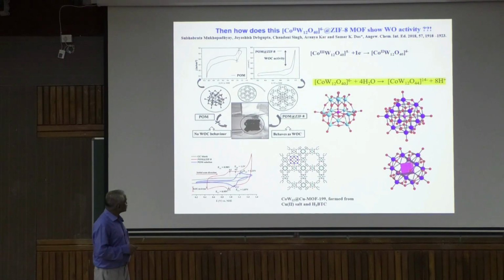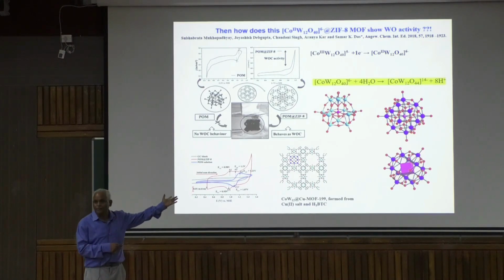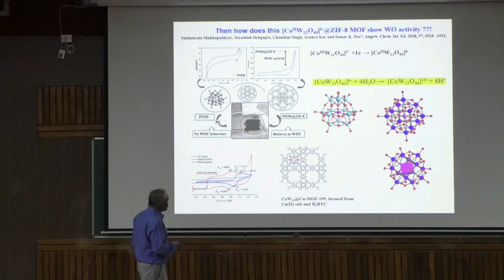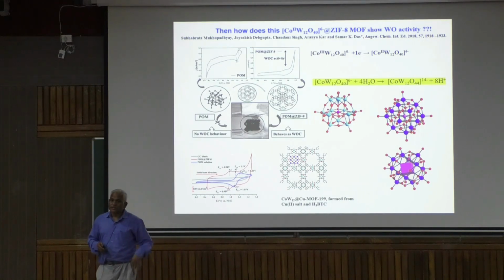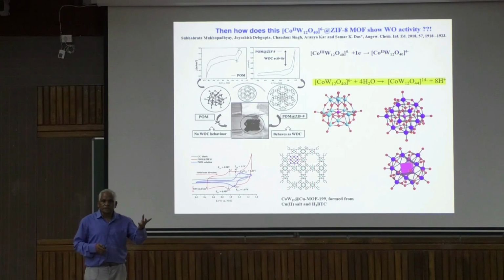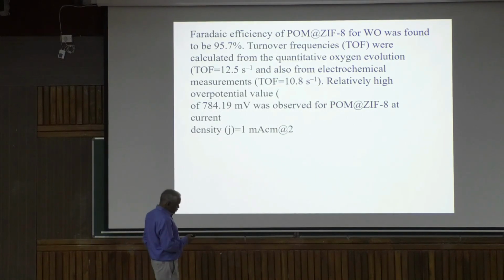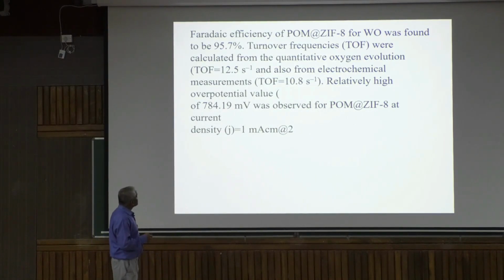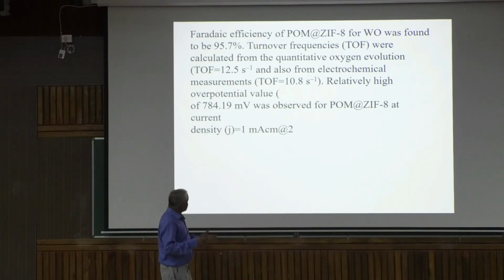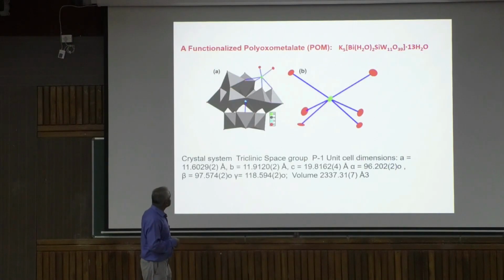So that is very interesting, the encapsulation that happened. And here is the very powerful tool, crystallography. Unless we did this, we would not have known what happened in the earlier case. Okay. So this way the story begins, and you can see how encapsulation makes a difference. A compound which is electrochemically inactive towards water oxidation gives water oxidation, but by getting hydrolyzed. And we found out all these parameters: turnover frequency 10.8 moles of oxygen per second is not bad. Faradaic efficiency is very good, close to 100%. So it's a good catalyst and works in neutral pH.